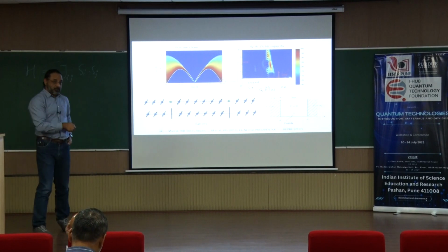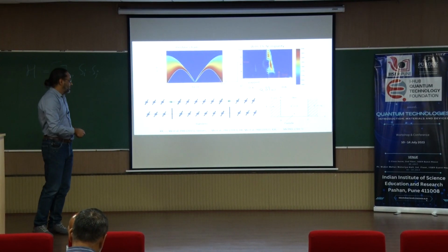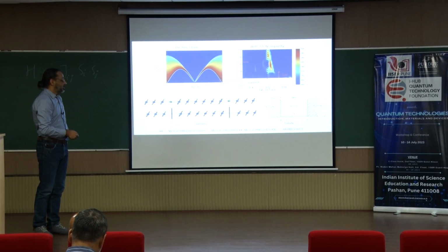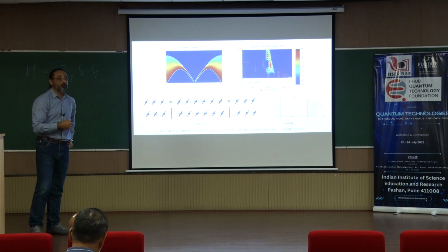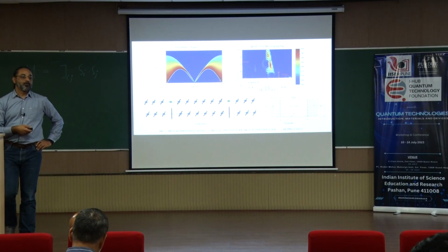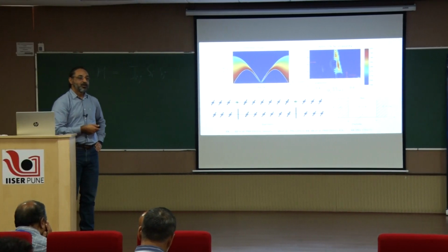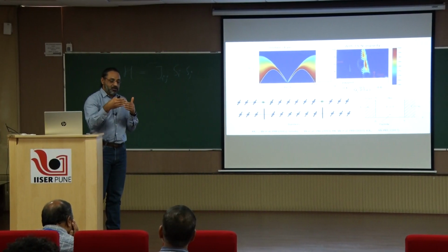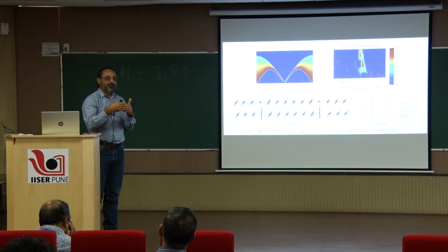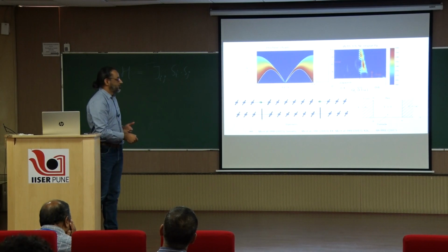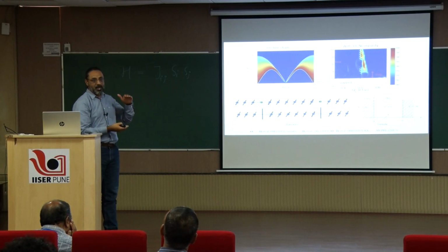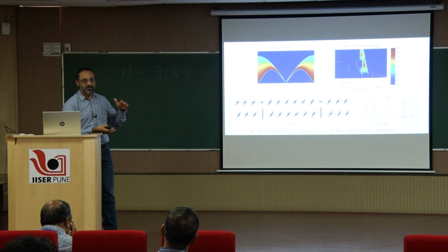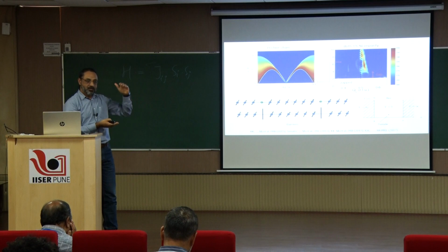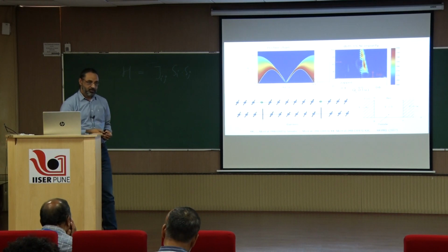To verify that what you have hypothesized is correct, you can change the impurity concentration. For instance, from 0.1% you can make it 0.25%, maybe 1%. By doing that, you are changing the length of the box. When you change the length of the box, what happens to the gap between the ground state and the excited state? As you squeeze the box, the energy gap increases, and you see that in your experiments.